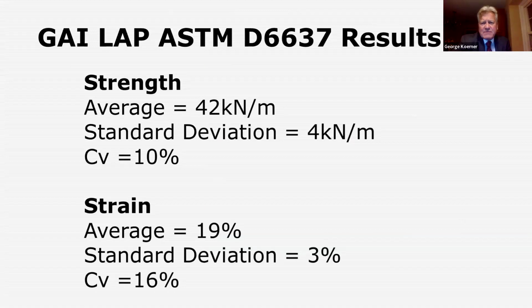For ASTM 6637, the results for strength for this particular material, an average of about 42 kilonewtons per meter. The standard deviation was 4, with a coefficient of variation of 10. So I think we did quite well. This was tested in 2020, and I'm quite proud of this set of data.